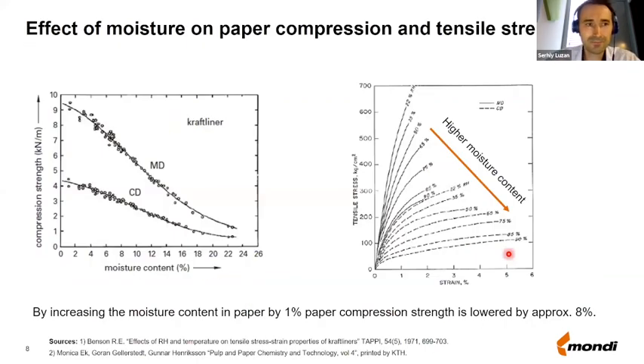So when the humidity is changing, we are changing the amount of moisture in the air. And as we change the amount of moisture in the air, the paper has to come into equilibrium with the surrounding environment. So if the relative humidity goes up, paper starts to absorb some humidity, and the moisture content in paper increases. And if the moisture content in paper is increasing, then the strength of paper is going down. Here you see an example for brown kraftliner, which shows how the compression strength is changing with the increase in moisture content. As the moisture content goes up, the compression strength goes down. And as a rule of thumb, you can remember that with an increase of moisture content in paper by 1%, the compression strength of paper goes down by on average 8%.